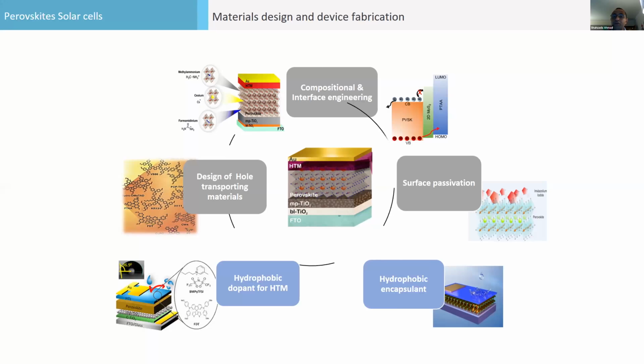Hydrophobic encapsulant: not mechanical encapsulant, but molecular encapsulants. There are some materials available which can encapsulate the surface. Then, hydrophobic dopant for HTM. HTM, the hole transport material, is the P-type material, but most of them require doping, and the doping is from lithium salt. This is a trade-off. So we developed some ionic liquid-based dopant, which doesn't compromise the stability of the devices while giving the same performance.